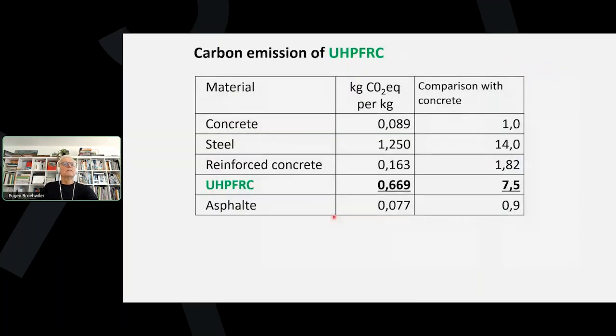Now, let's look at a very different property of UHPFRC. We should care about carbon emission in construction. And of course, UHPFRC, which is essentially cement and steel, has a rather high CO2 equivalent emission, which is 0.7 kilograms of CO2. Compared to concrete it is significantly higher, of course, but lower than pure steel. It is about 4 times higher than reinforced concrete. So this says already that once we work with UHPFRC, we should use about 4 times less UHPFRC than reinforced concrete if we want to have the same carbon emission amount for the same structural purpose.